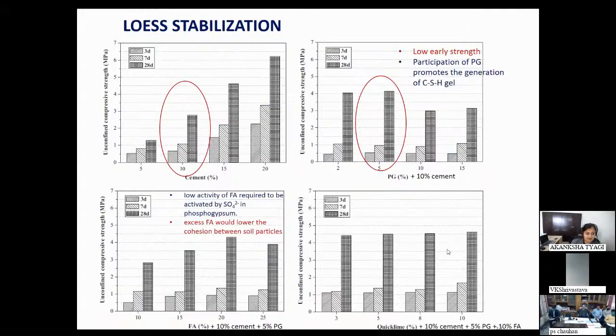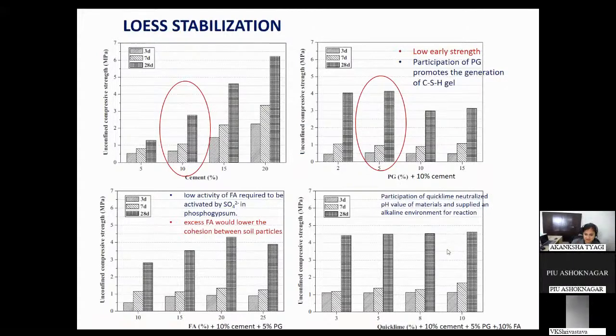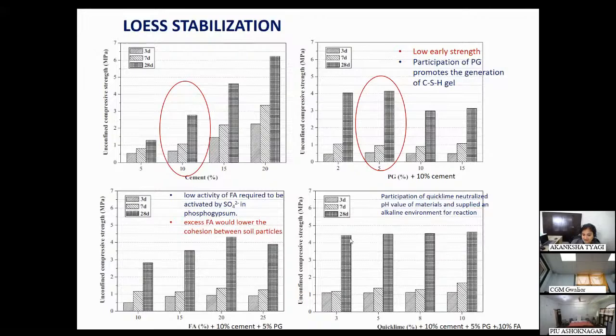Basically, the participation of quicklime is that it is known to neutralize the pH value of materials. Both the fly ash and phosphor gypsum are acidic materials. So quicklime is alkaline, and it provides a good environment for these materials to react. So when quicklime is added, there is a substantial increase. Even with 3% quicklime, there is a substantial increase in the strength. I mean, 3% looks sufficient from this study.